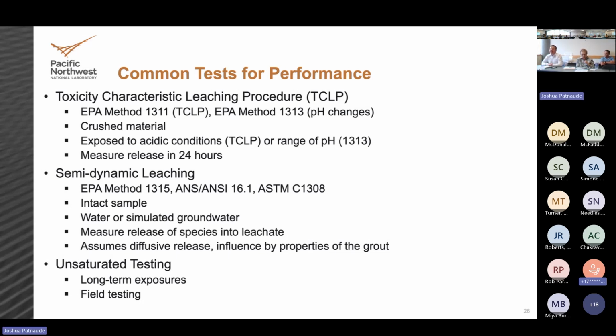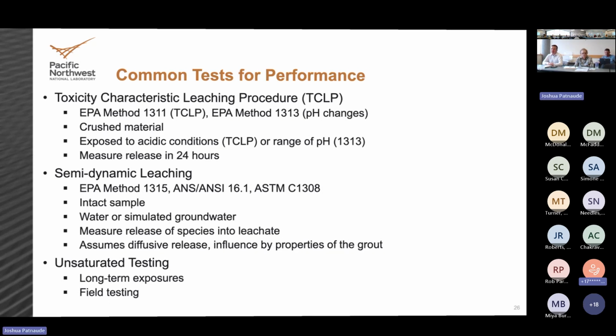I thought I had this as an animation, but some of the main leach tests are TCLP, the semi-dynamic leach test, and then to get to more real world conditions, especially in our application, unsaturated testing, which takes a very long time because you don't have a lot of water nearby. But again, we want to ensure that the models that we develop to predict long-term performance can replicate behavior, whether it's in short-term aggressive tests, longer-term representative tests, field tests, or analogs. We always try to build our story out so we grow confidence in the materials that we are providing data for folks to make decisions on.